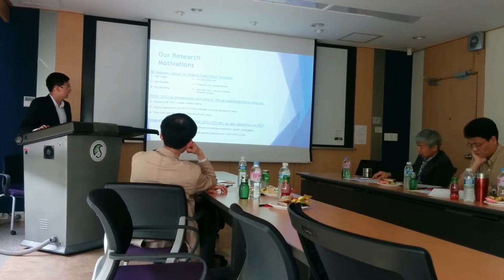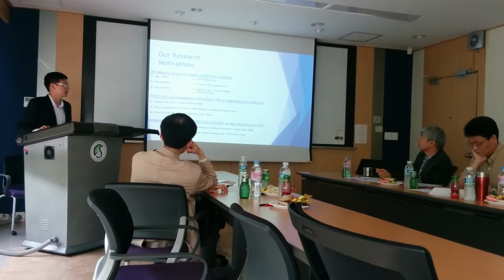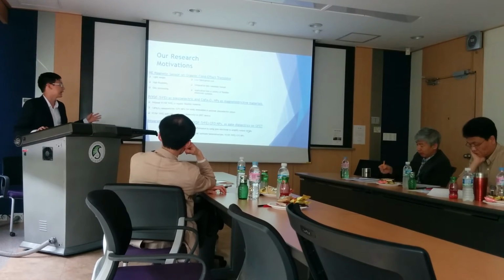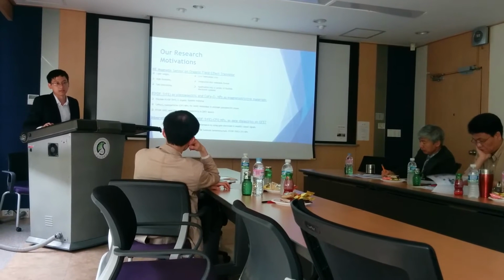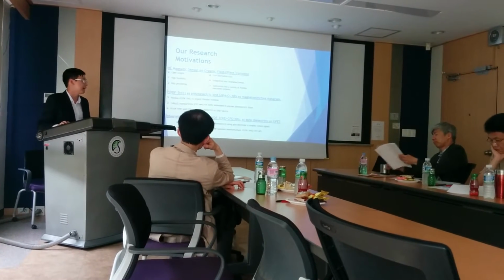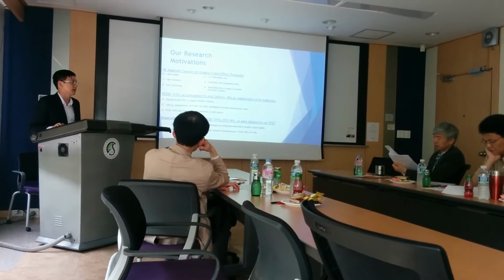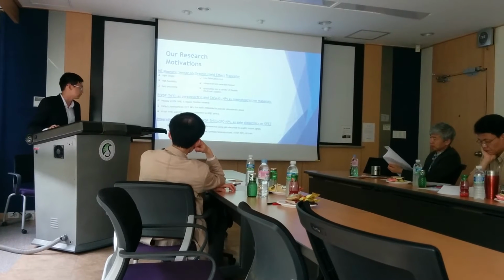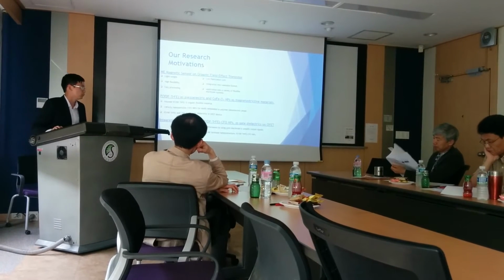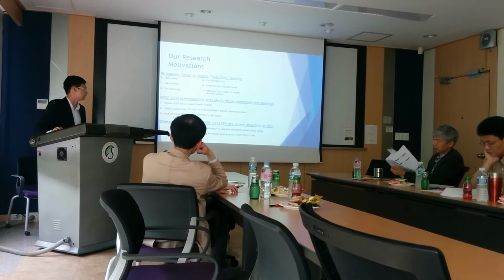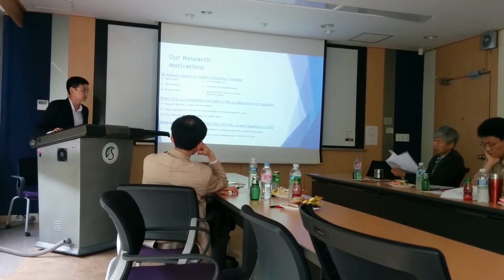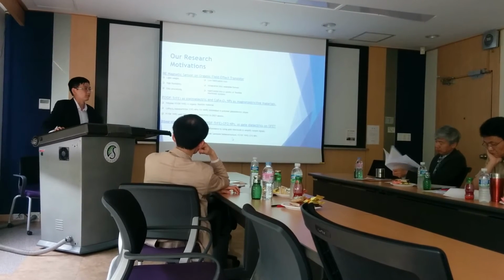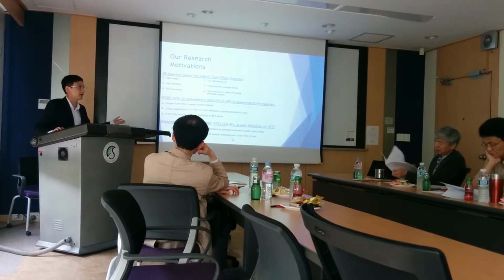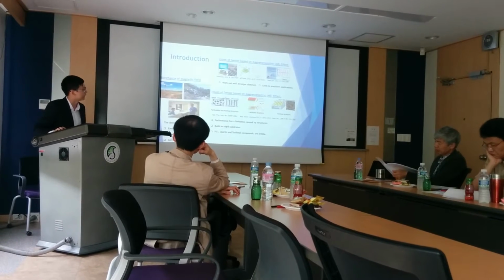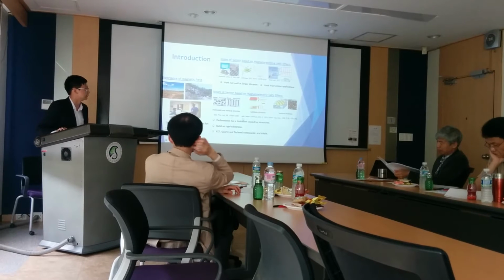If we integrate the ME composite as the gate dielectric on the OFET, we can solve the limitation of the ME performance by using the gate electrode to amplify the output signal. Moreover, we use the ME composite as a laminate structure to avoid the leakage current compared with the particulate structure, as I showed here.